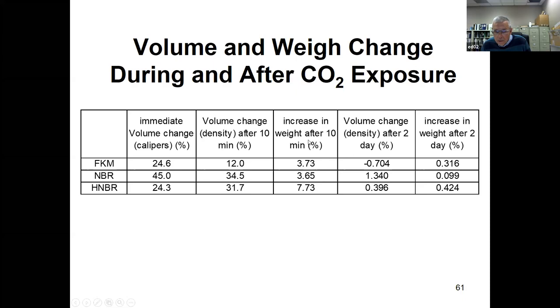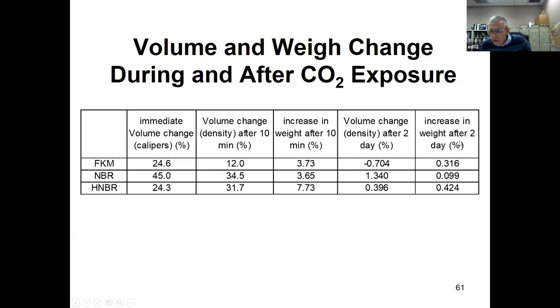Weight increase after 10 minutes of degassing was approximately 4%, 4%, and 8% for the three compounds respectively. Two days after degassing, volume change showed slight decreases or increases, and all compounds showed a slight increase in weight.